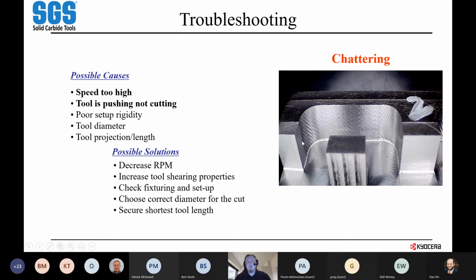So using a smaller diameter tool will help with that, because you're not going to have that whole radius of that tool engaged as you're going around that corner. So it's just going to cut more efficiently, and it's going to tune that out. Now, on the flip side of that, you have a really small diameter tool with a ton of flute length. Now you have a flimsy or a less rigid tool. It's going to have more deflection in it. So as you're running these cuts, it's going to push off more, and it could start to bounce some on its own. And that's where those different layers of chatter reduction really come into play,